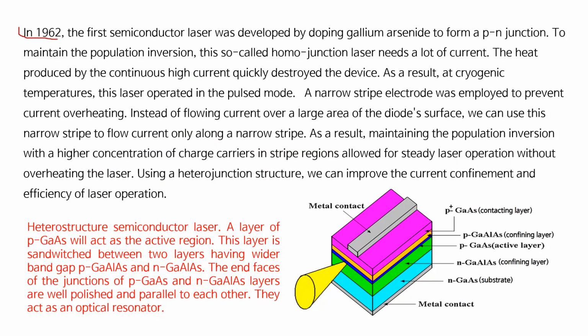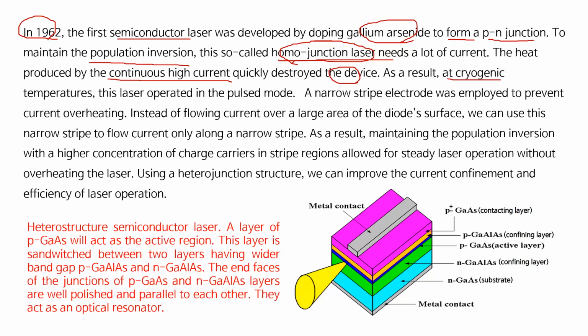In 1962, the first semiconductor laser was developed by doping gallium arsenide to form a p-n junction. To maintain the population inversion, this so-called homojunction laser needs a lot of current. The heat produced by continuous high current quickly destroyed the device. As a result, at cryogenic temperatures, this laser operated in the pulse mode. A narrow stripe electrode was employed to prevent current overheating.